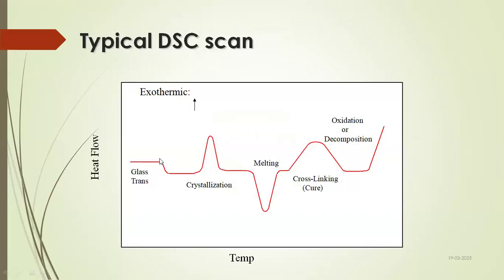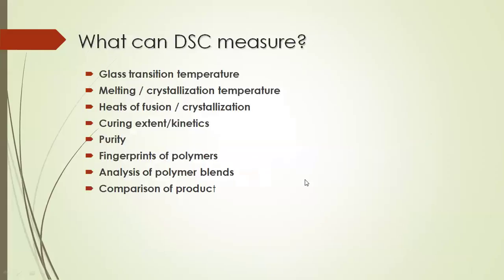A typical DSC curve looks like this: you get a glass transition temperature, you get a crystallization, you get a melting, you get a cross-linking, and then it decomposes. But remember, this decomposition stage should never appear in DSC, because all this decomposed material is going to settle in your DSC cell, which is a very hazardous and dangerous situation. So always run a DSC below your TGA degradation temperature. First, you take a TGA of your unknown sample, find out the degradation temperature, and always run a DSC 20 to 30 degrees below your degradation temperature, so that the degradation stage doesn't occur in the DSC. You will never allow any material to degrade or decompose in your DSC cell.